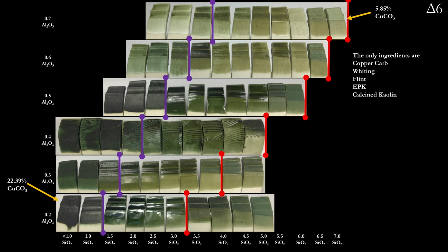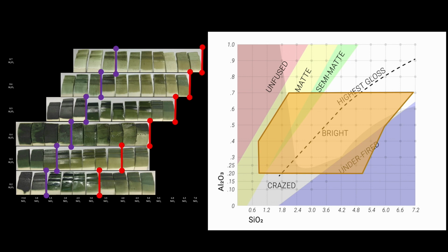So we did 60 tiles total with a 0.2, 3, 4, 5, 6, 7 alumina level, which is on the right-hand side, and then on the Y, we have increases of silica. Of course we moved up diagonally because the glazes are referenced to: are they matte? Are they gloss? We wanted to stay in that gloss area. So that's the 60 tiles, and then we plotted them on the area that they represented on Stull according to their chemistry and their silica to alumina proportions. So again, we see gloss where we were supposed to see gloss.